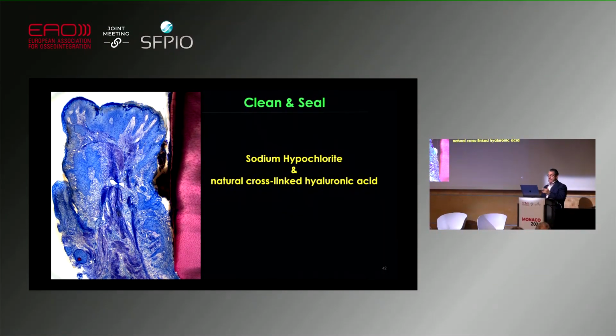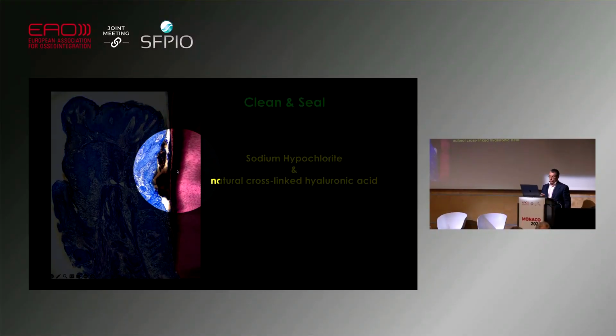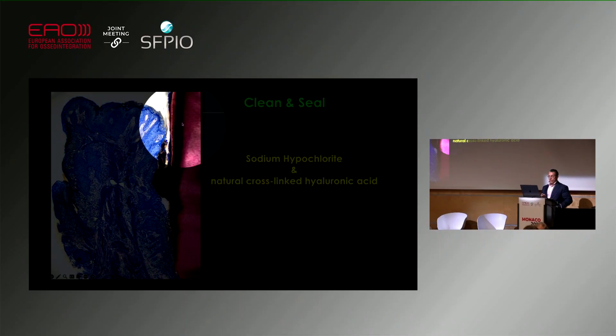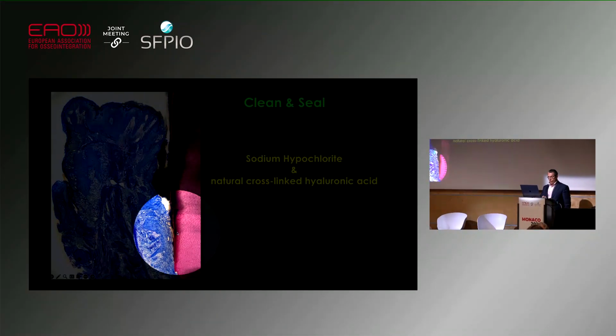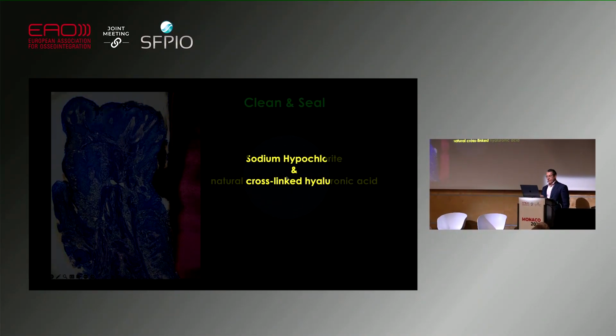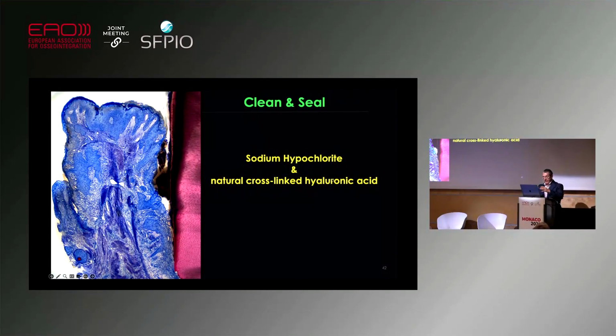But in fact, based on this study that I presented to you, we have the so-called clean-and-seal concept. That's quite simple. We clean a pocket using the sodium hypochlorite that softens the soft tissue and softens the calculus. We remove the granulation tissue, we remove the calculus, and then we instill the hyaDENT BG, the cross-linked hyaluronic acid, in the pocket and let it heal. And this has been beautifully demonstrated also by my colleague Dr. Ramanauskaite, who has performed a pivotal clinical study on this, and she will present the data.